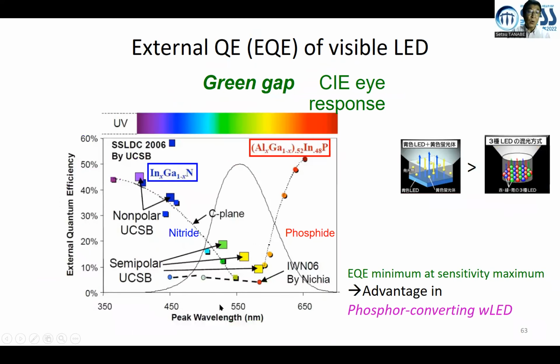This is the wavelength variation of external quantum efficiency of nitride LED and phosphide LED. You can see nitride has high quantum efficiency around 400 to 450 nanometer, the blue region, and not green, by increasing indium content, narrowing the band gap. In the case of phosphide, aluminum-poor composition, indium-rich composition has a high quantum efficiency, but widening the band gap, approaching orange-yellow, quantum efficiency drops.